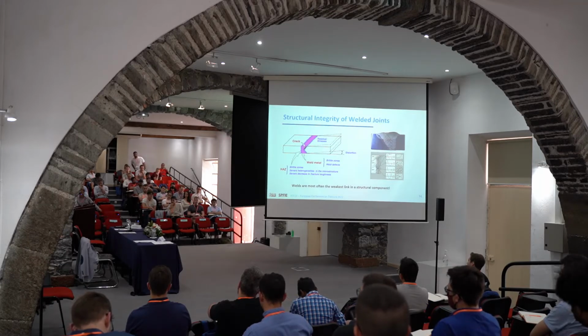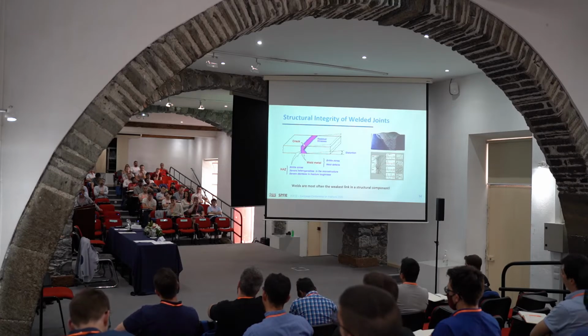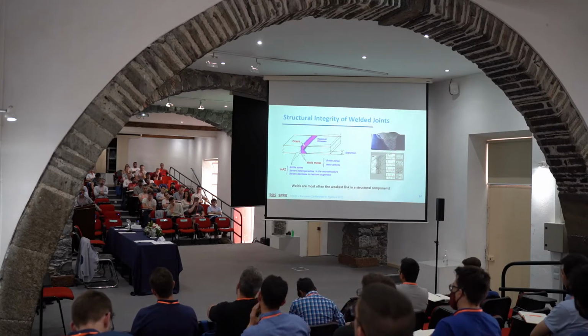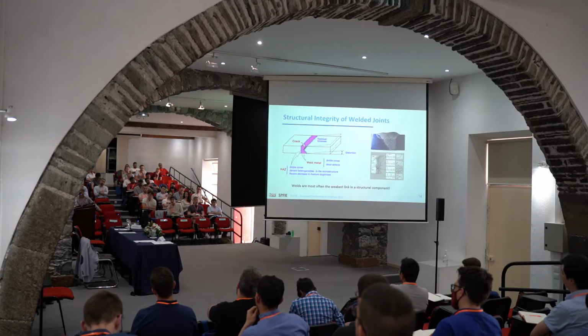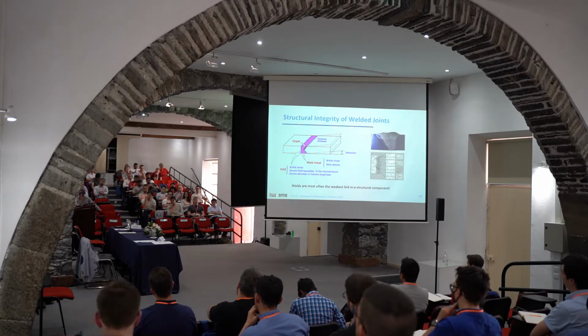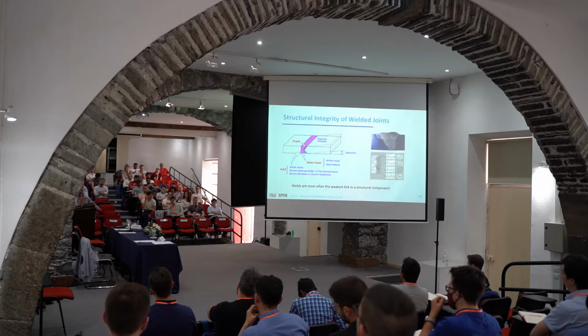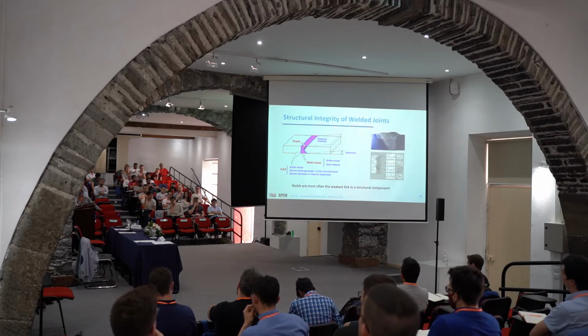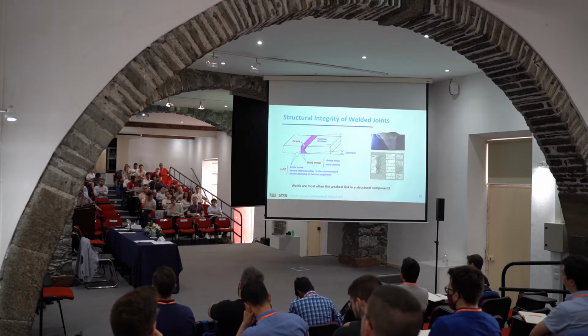Especially with robots and automatic welding. However, welding is still the weakest link. So you don't want to board an aircraft which is welded, because if a crack develops during the flight, the crack will just run as long as it has material to propagate, and of course enough energy. Okay, this is Griffith's principle.